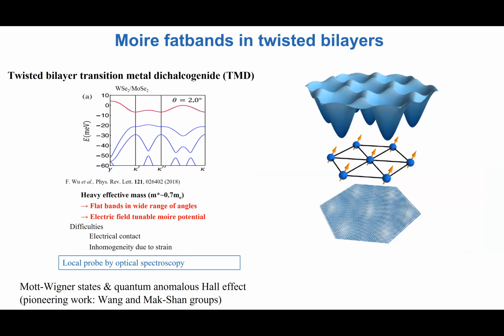And here I show a calculation of valence band Moire bands, and this is molybdenum diselenide, tungsten diselenide. This is at 2 degrees. You see that there is a relatively flat band with a bandwidth of 10 millielectron volts, isolated from the more dispersed bands. Okay. And what is nice in this system is that there is no magic angle like you need in graphene. So all angles are in principle as good, and you can choose the twisting angle as a tuning parameter of what your lattice periodicity would be, which in turn would determine how strong interactions would be as compared to the hopping.